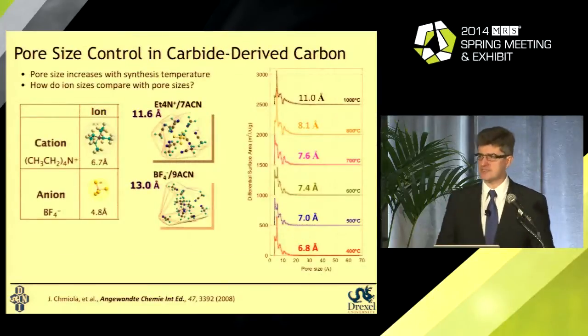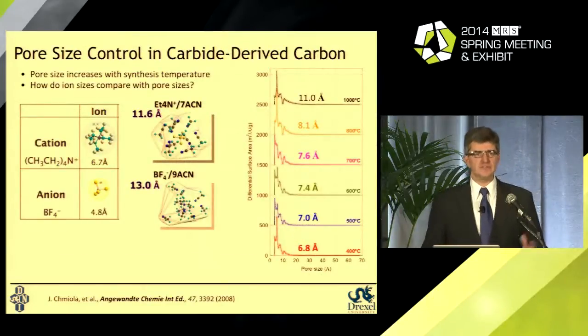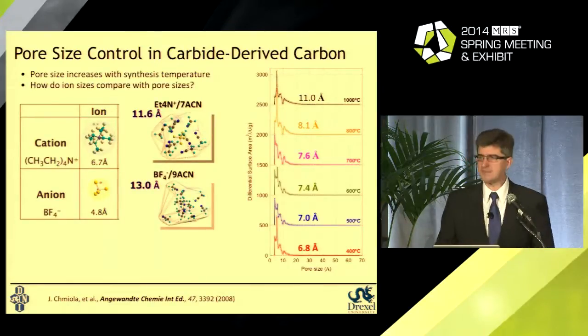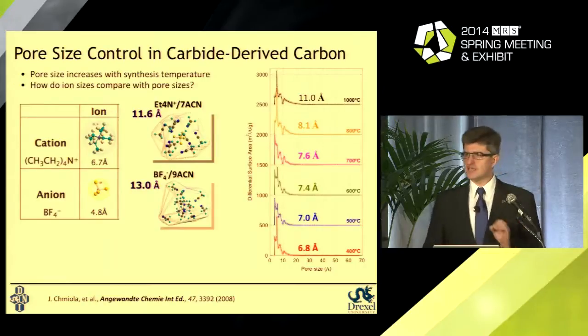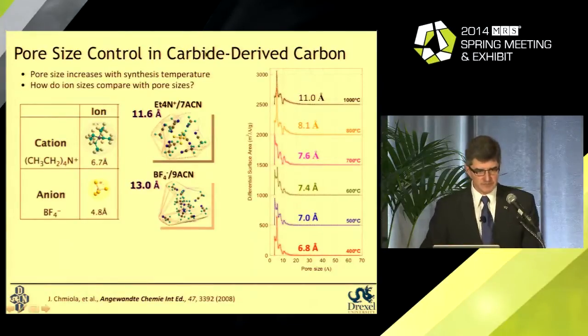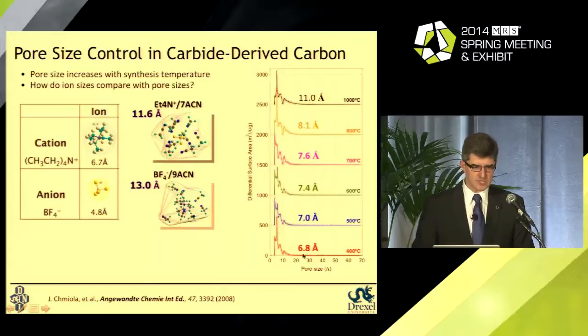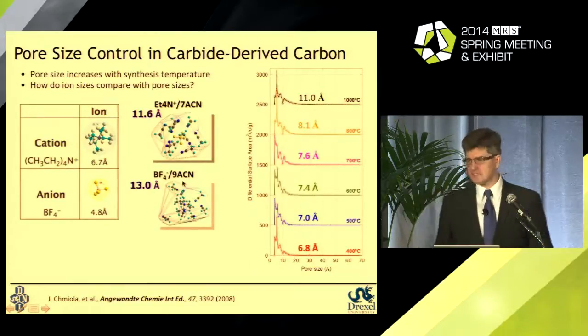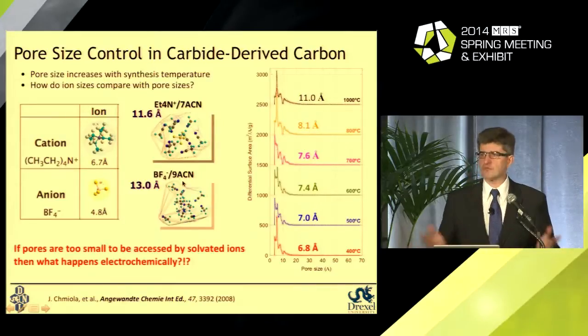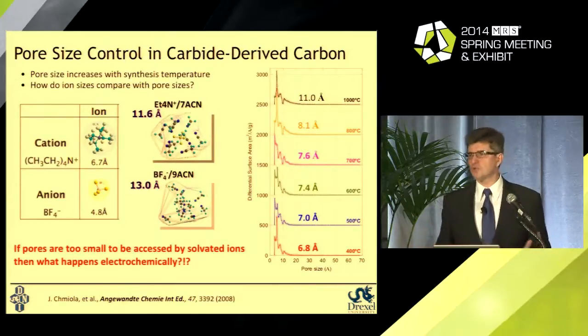So what we did when we started to work in this area, and we developed carbide-derived carbon materials with controlled porosity, we just wanted to check what happens if we control the pore size in carbon network with a high accuracy, much higher than people can do it in conventional carbon materials here. And we produced a number of carbons. You see the pore size is changing from less than 7 angstrom to about 11 angstroms, with maximum pore sizes being actually smaller than the solvated ion size here. And the question we ask here, what happens if pores are just too small to accommodate ions?